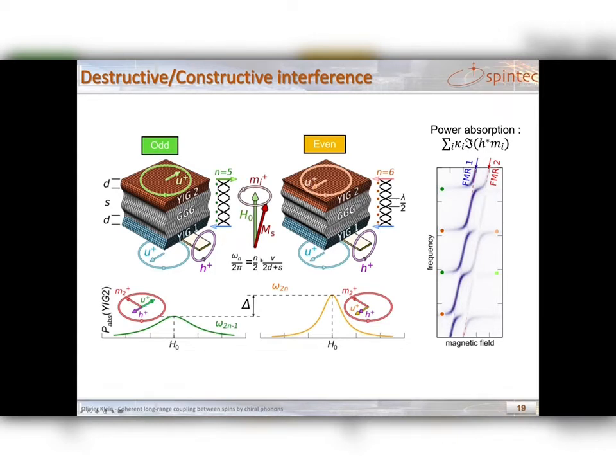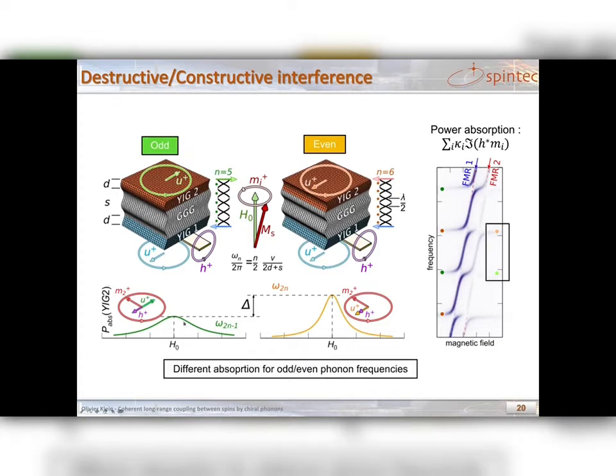However, for even phonon, both the phonon and the microwave field drive the top layer and therefore are in phase, and therefore the signal increases. This can be shown here by an increase of power absorption in one case and a decreased power absorption in the other case. And what you can see is that for even phonon the signal intensity is larger than for odd phonon, and this is a kind of interference experiment.